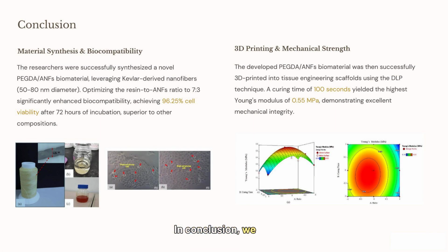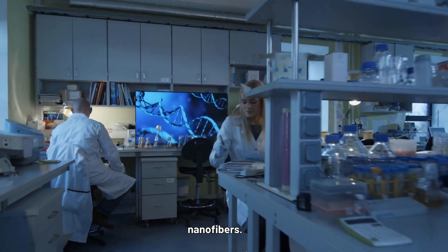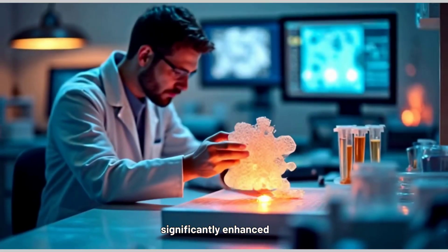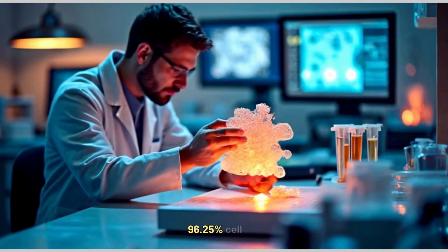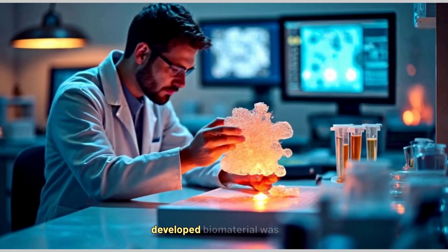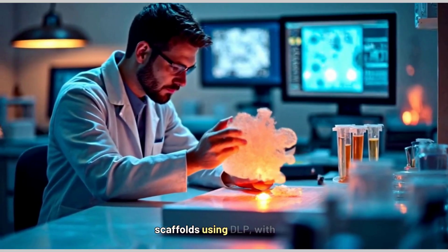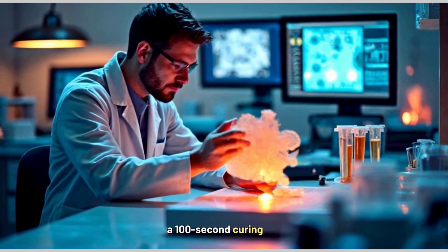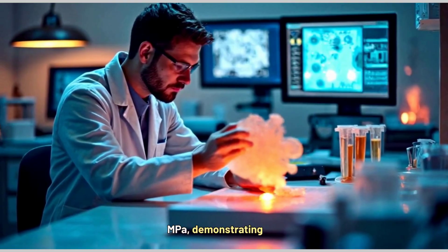In conclusion, we successfully synthesized a novel PEGDA/ANFs biomaterial, leveraging Kevlar-derived nanofibers. Optimizing the resin-to-ANFs ratio to 7:3 significantly enhanced biocompatibility, achieving 96.25% cell viability after 72 hours. The developed biomaterial was successfully 3D printed into tissue engineering scaffolds using DLP, with a 100-second curing time yielding the highest Young's modulus of 0.55 MPa, demonstrating excellent mechanical integrity.